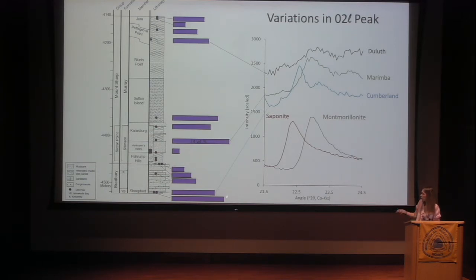Cumberland in blue is from the base of the section. Marimba in green is from the middle of the section, and then Duluth in black is from the top of the section. And you can see that the 02L peak for Cumberland is furthest to the left, so has the highest d spacing, and it's most consistent with a saponite. And then moving up section, that 02L peak moves to the right, suggesting that we are moving from trioctahedral phyllosilicates to dioctahedral phyllosilicates going up section.